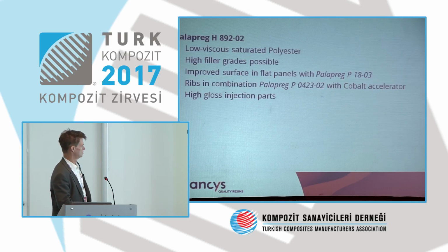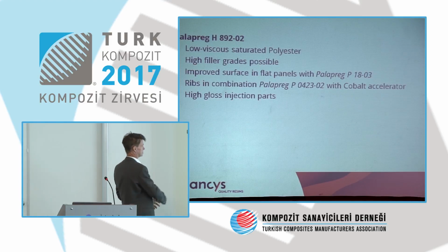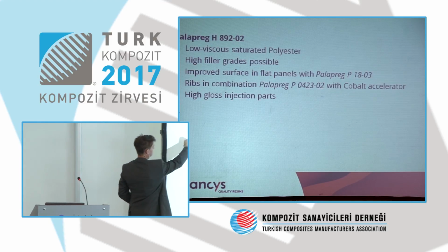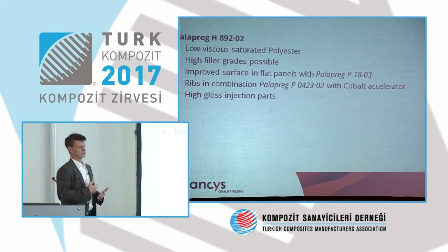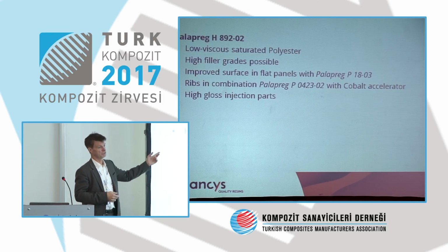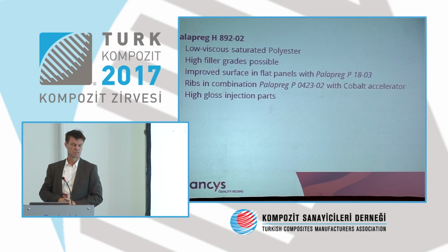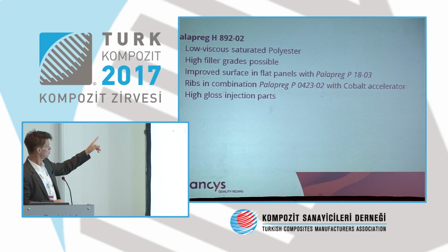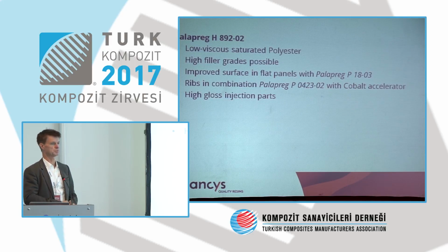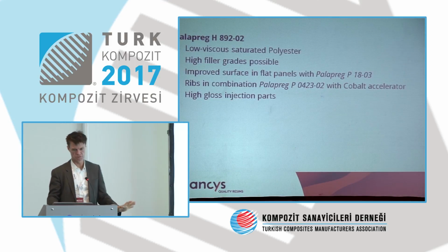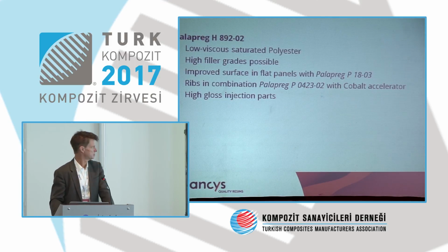So this is the message here. It's also excellent product and excellent performance, not only in compression molding, but also in injection molding. And by using these two components, for example, you can expect a high gloss, really glossy surface. If the mold is good, you see also excellent result after the molding with a good glossy surface.